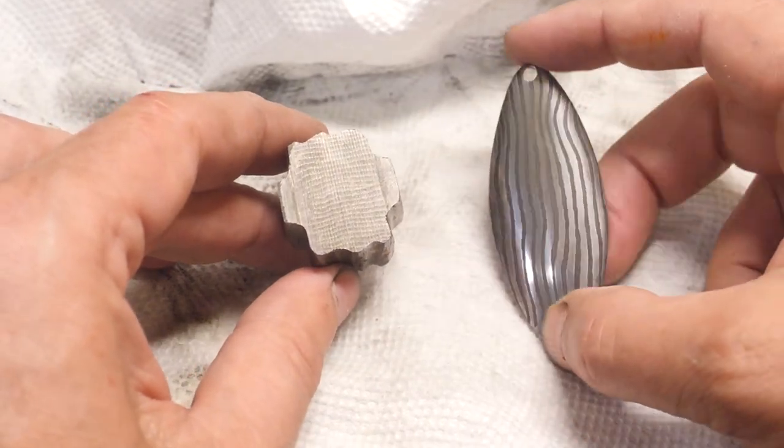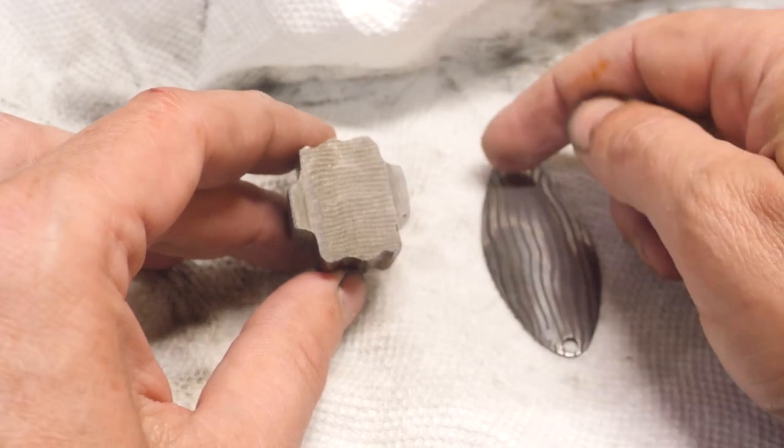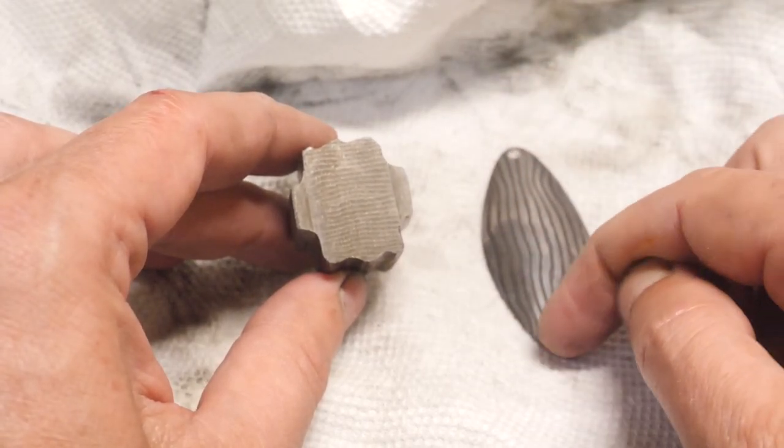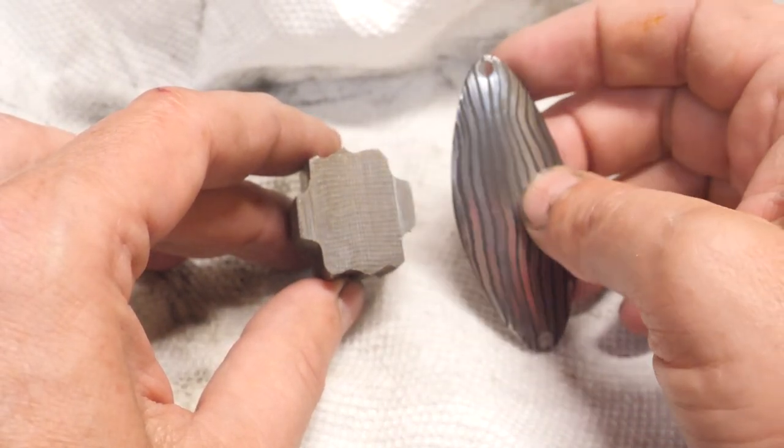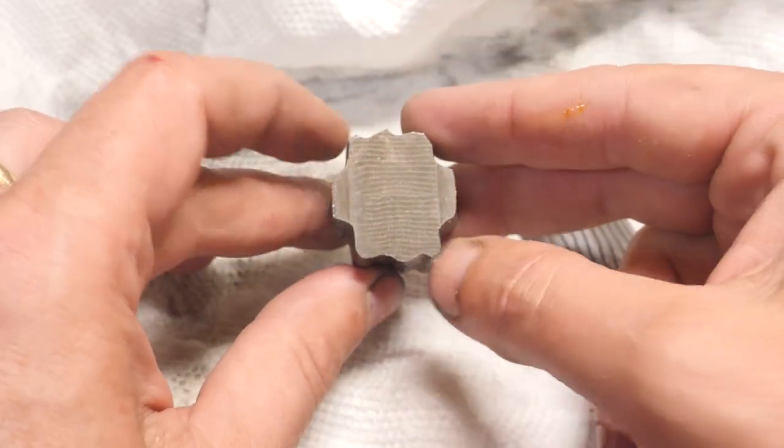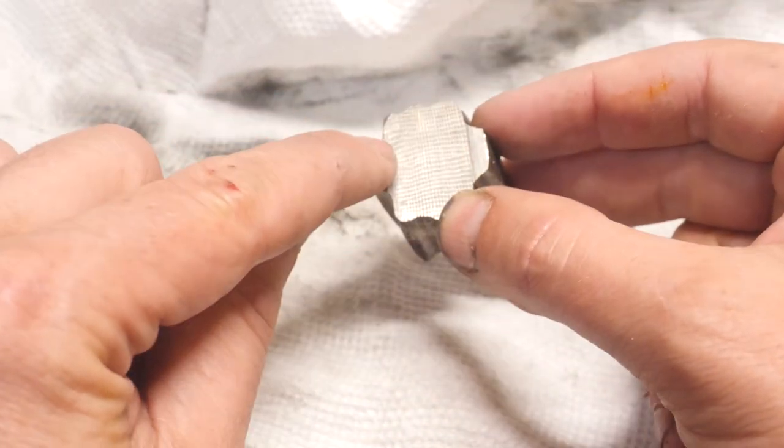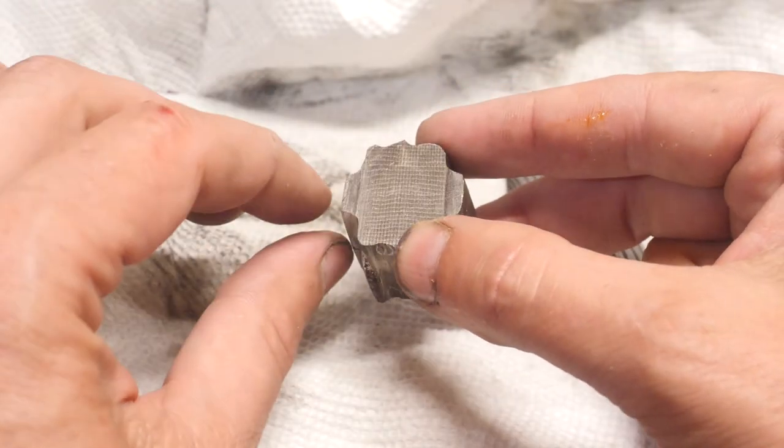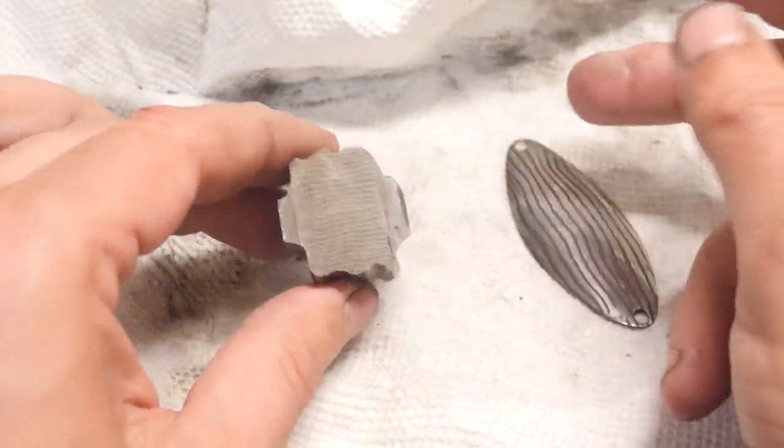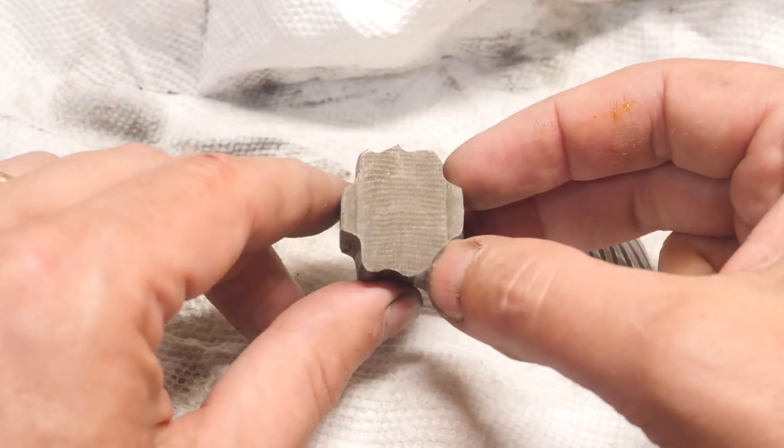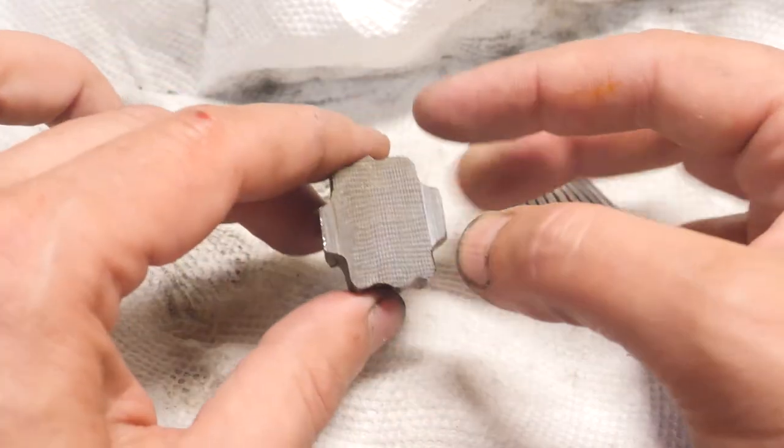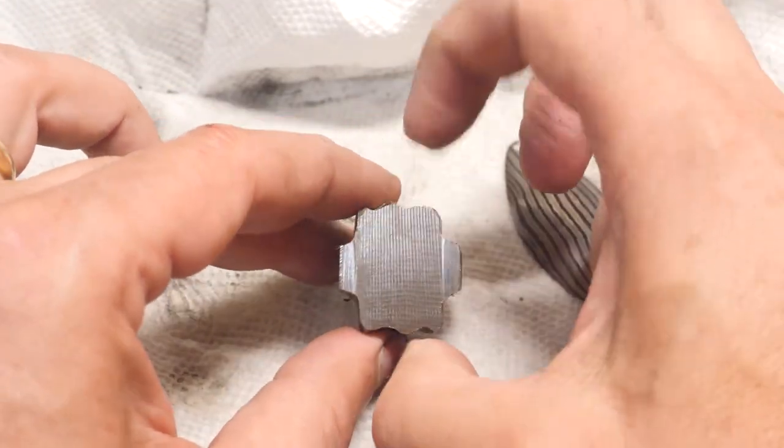The stainless popped off the tips of this one and I really would like the stainless around the holes, the eyelet holes, for lots of reasons. So I'm going to try one more time. Even though these welds are solid now, under heat and pressure they're just probably going to pop like they did here. So what I've done is I've ground the stainless off the ends and we're going to compress it in this direction such that there's no pressure to be exerted here as we flatten it out.